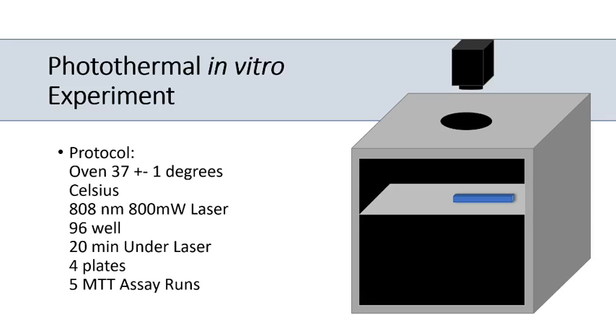We irradiated each of the wells for 20 minutes, the same as we did for our photothermal properties. And we did 4 plates with each type of sample. So that's 4 of the thulium NGQDs, 4 of the molybdenum disulfide, and 4 of the GQDs. The reason we did this is because we wanted to make sure that this was reproducible, and it wasn't just one fluke plate of cells that worked really well or didn't work really well. And then we ran each of those plates in the MTT assay 5 times.